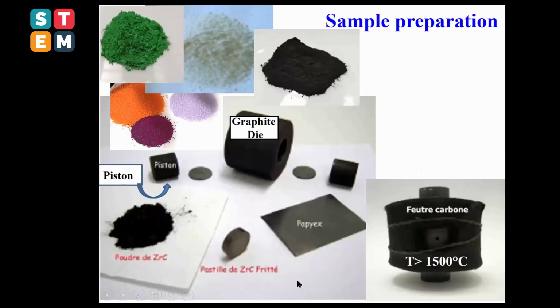Well, to prepare the samples, you are going to combine the powder, which you put inside the die, here graphite die basically, and you're going to use also some graphite piston here, but put the graphite foil around before putting the powder inside. But when you want to heat some materials above 1500 degrees C, you should also put some graphite around to save the temperature and also for homogeneous temperature.